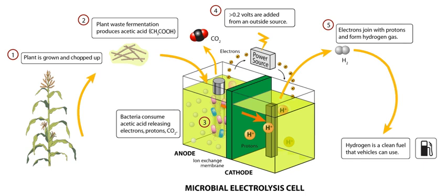Hydrogen production has reached up to 3.12 m³ H2 per m³ per day with an input voltage of 0.8 volts. The efficiency of hydrogen production depends on which organic substances are used. Lactic and acetic acid achieve 82% efficiency, while the values for unpretreated cellulose or glucose are close to 63%. The efficiency of normal water electrolysis is 60 to 70%. As MECs convert unusable biomass into usable hydrogen, they can produce 144% more usable energy than they consume as electrical energy. Depending on the organisms present at the cathode, MECs can also produce methane by a related mechanism.